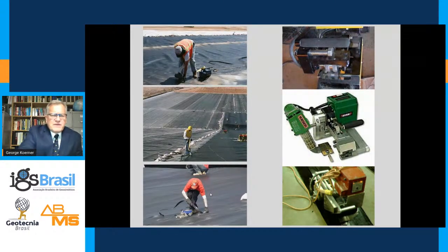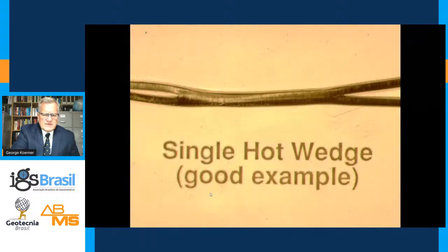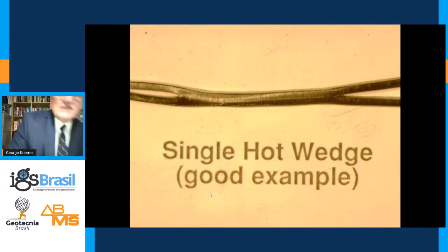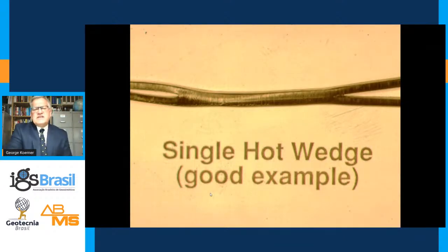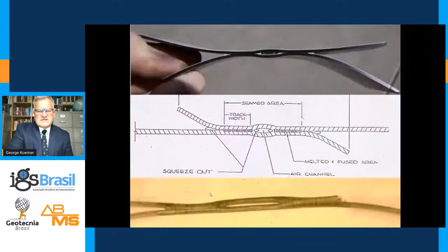Very different between longitudinal and butt seams. The butt seams on the roll edges are typically done with flat, solid wedges, where the longitudinal seams are done with split wedges with DualTrack hot wedge seaming. A single wedge seam is shown here. You see the area that's bonded plus the squeeze out.